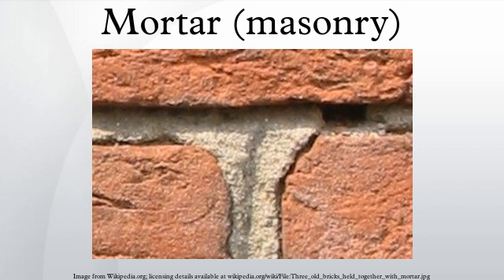Fire-stop mortars are mortars most typically used to fire-stop large openings in walls and floors required to have a fire resistance rating. They are passive fire protection items. Fire-stop mortars differ in formula and properties from most other cementitious substances and cannot be substituted with generic mortars without violating listing and approval compliance. Fire-stop mortar is usually a combination of powder mixed with water, forming a cementitious stone which dries hard. It is sometimes mixed with lightweight aggregates such as perlite or vermiculite, and sometimes pigmented to distinguish it from generic materials in order to prevent unlawful substitution and enable verification of the certification listing.